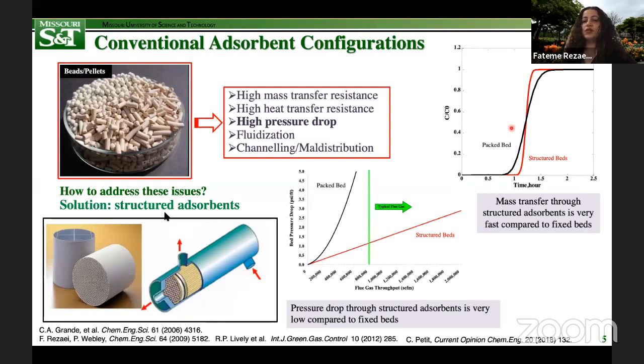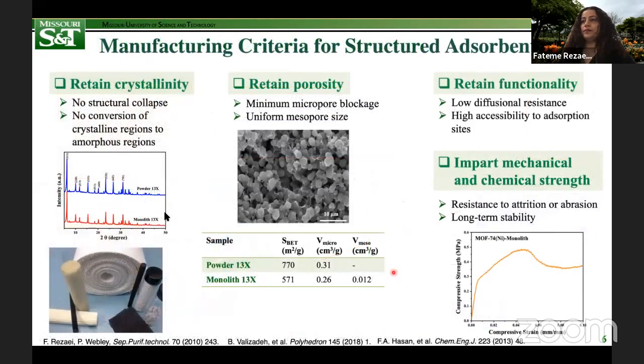Also, as this figure shows, a key advantage of structured adsorbents in comparison to traditional packed bed systems is that pressure drop through these beds will be correspondingly lower, especially for higher gas throughputs, which will in turn reduce draft fan costs significantly. And lastly, with these contactors, the chance of fluidization or channeling or maldistribution occurring will be substantially lower than that of traditional packing systems, mainly because of the uniform flow pattern through these beds.